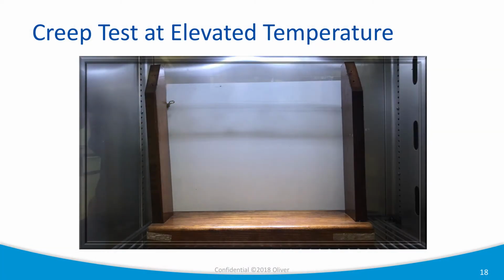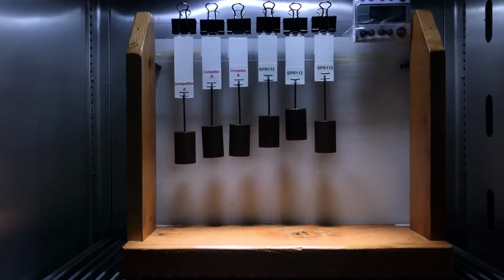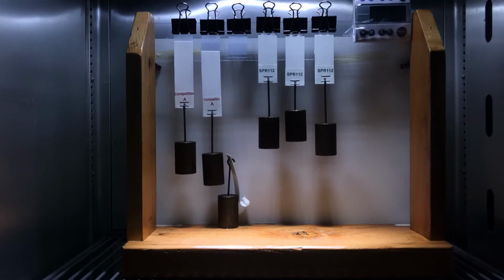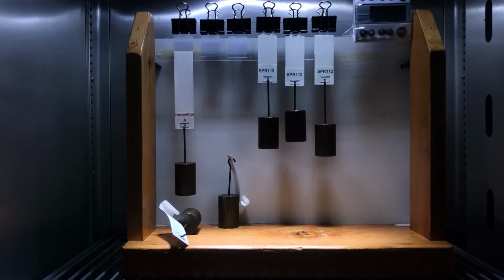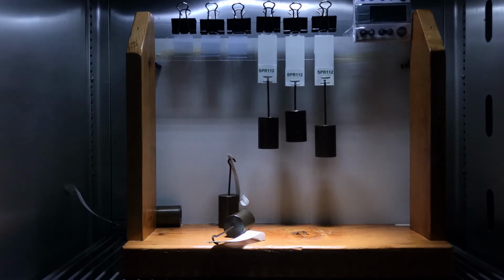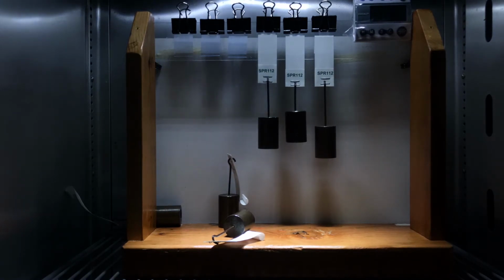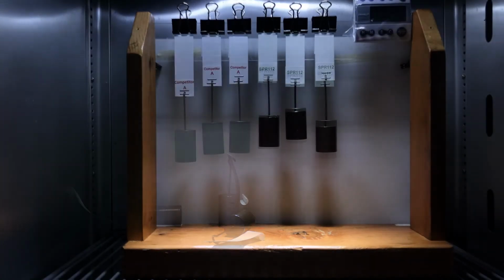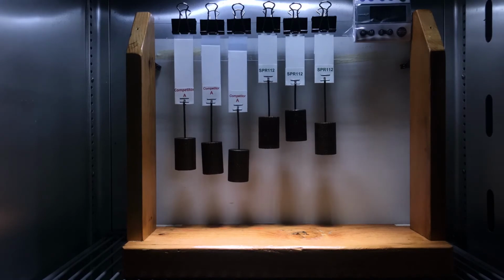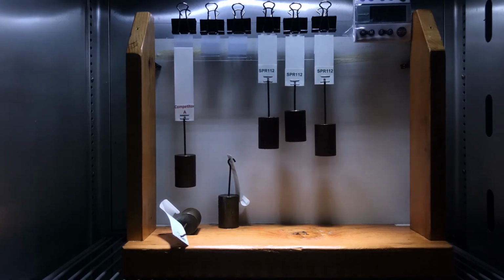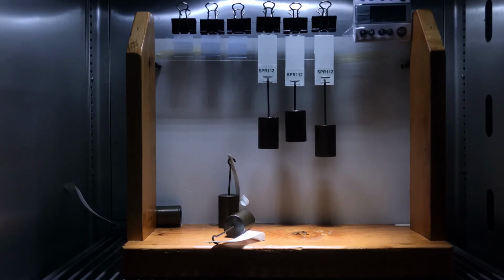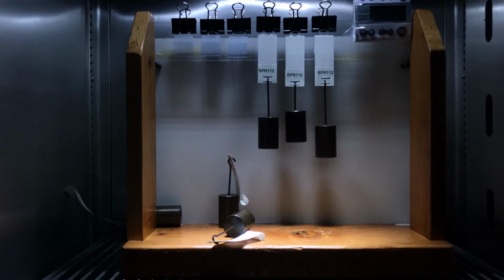So here's a test that we do. I'll run this a few times so you can see it. This is inside a humidity chamber, with temperature and humidity control, so we can run it at 55 C, 95% relative humidity. We hang weights on it, so this mimics stress under those conditions. Let me just go back and start it again. Here we go. You can see the legacy material in this time lapse was dropping off fairly quickly, and we had an improved version optimized for seal creep on the right side, and you can see there was quite a bit of difference in its performance.